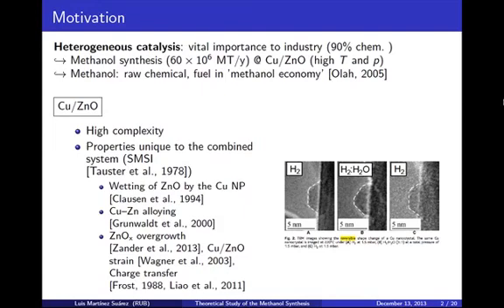The copper zinc oxide catalyst, consisting of copper nanoparticles supported on a zinc oxide matrix, shows high chemical complexity and properties unique to the combined system, so-called strong metal-support interactions. In particular, environment-dependent morphological changes were reported from experiments, but also strain at the interface and charge transfer effects.